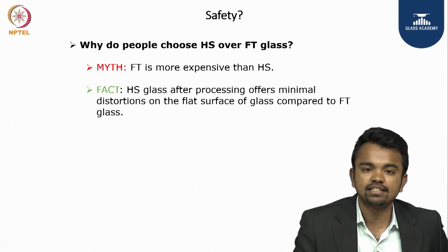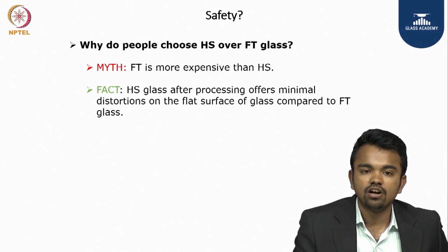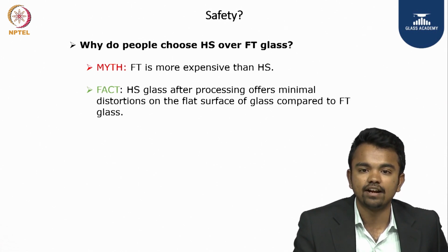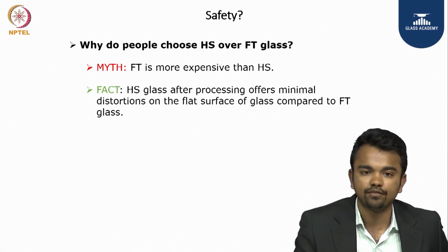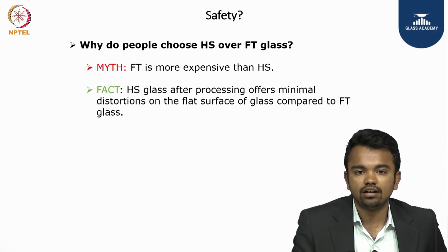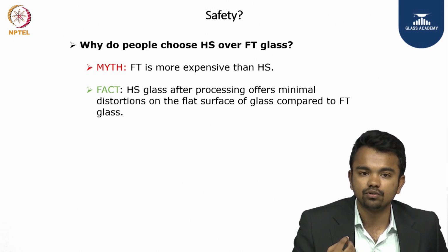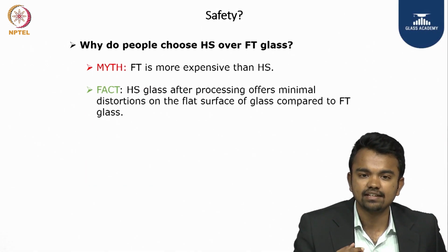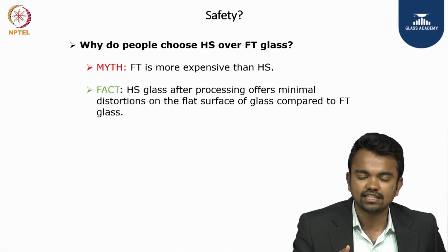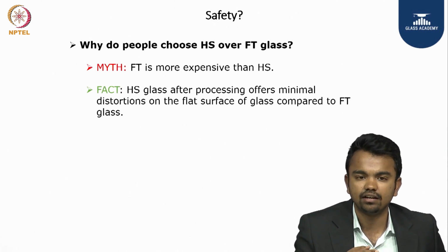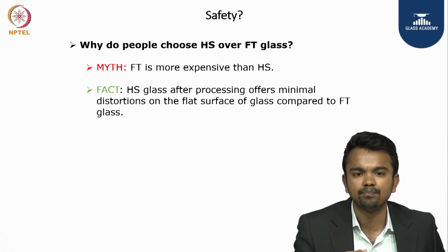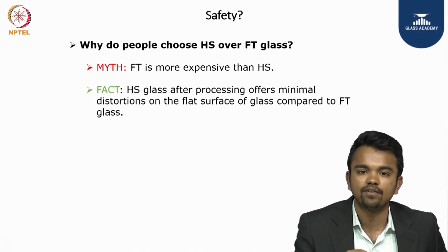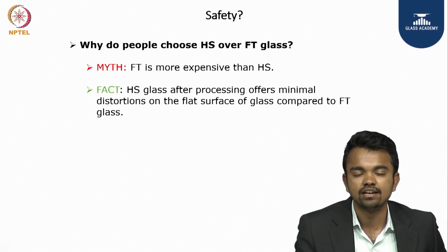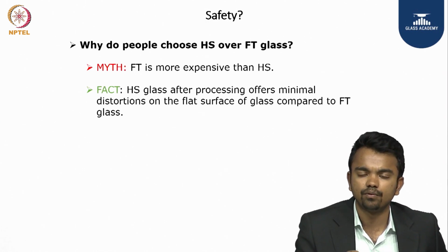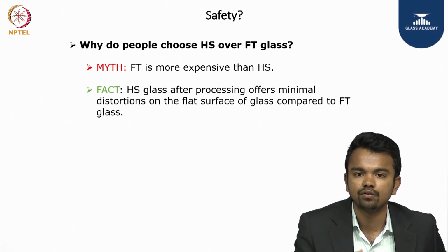The fact is that heat strengthened glass after processing offers minimal distortions on the flat surface of glass compared to fully toughened glass. Whenever glass is subjected to any heat treatment, some distortions are created. Heat strengthened glass, which is slightly inferior in terms of resistance against impact amongst these two, will have minimal waviness and minimal distortions on the flat surface compared to fully toughened glass. So this is one of the reasons why heat strengthened glass is chosen over fully toughened glass.